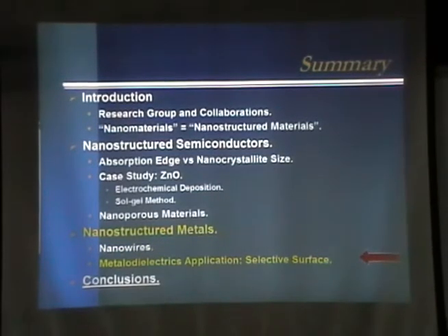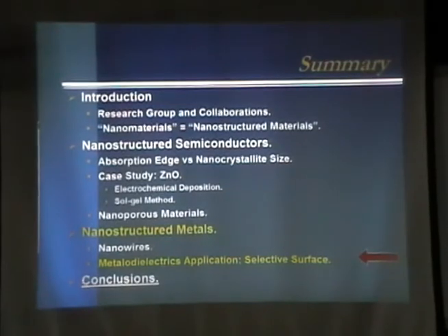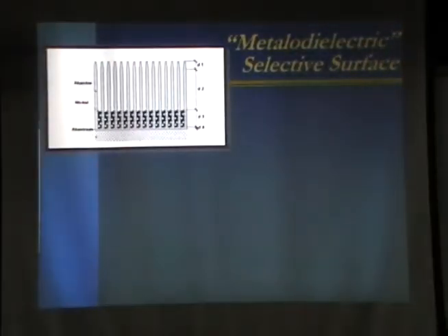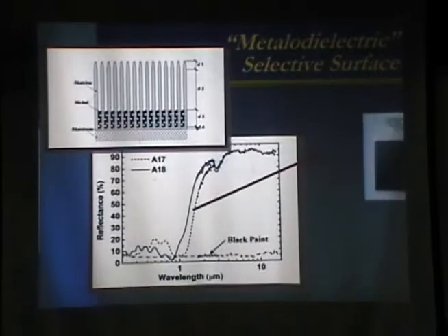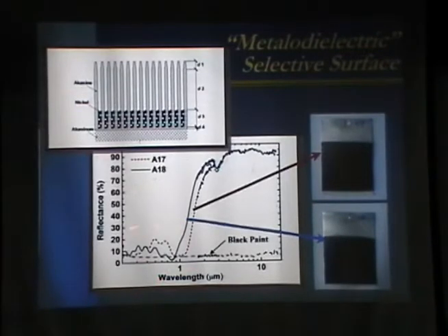Well, to end this panoramic talk on examples of things we are working on here, I want to show you what we are currently working on, trying to fabricate selective surfaces for solar energy to thermal conversion. The most common example is to have inside this porous structure some metal aggregation, for example nickel, that gives you this typical spectrum that absorbs light in the visible range, while it reflects light in the infrared, so you have a selective behavior quite appropriate for energy heating, right?